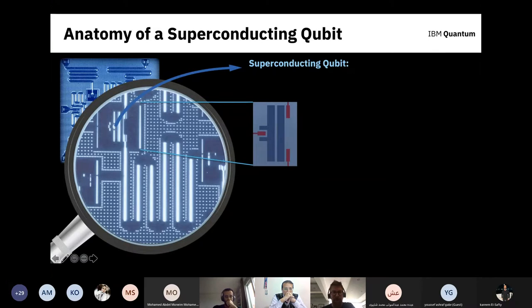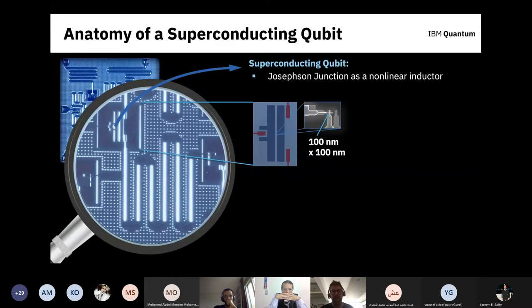We still have many superconducting qubit devices online that are free for anyone to use. Looking closer at the chip, the qubits themselves live in these little squares we call pockets. The qubits look like an equal sign rotated 90 degrees. The equal sign part represents the capacitor of the circuit — two metals with an electric field between them. There's a special, much tinier element in between that we fabricate differently, made out of aluminum, which becomes superconducting below 1.2 Kelvin.